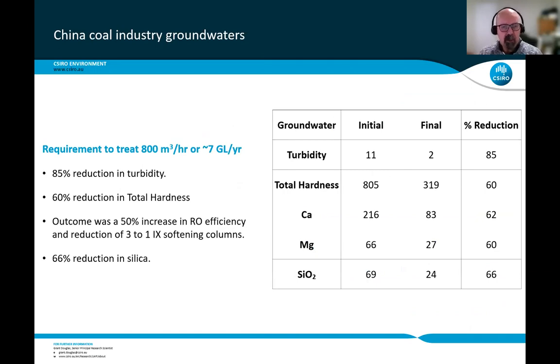So what did we get in terms of performance? Well, turbidity was removed or reduced by about 85%. We had around about a 60% reduction in total hardness, and the constituents there, calcium and magnesium, were removed by a similar amount. And we had about a 66% removal in silica. But collectively, that total hardness and silica removal gave the plant operator around about a 50% increase in RO efficiency.